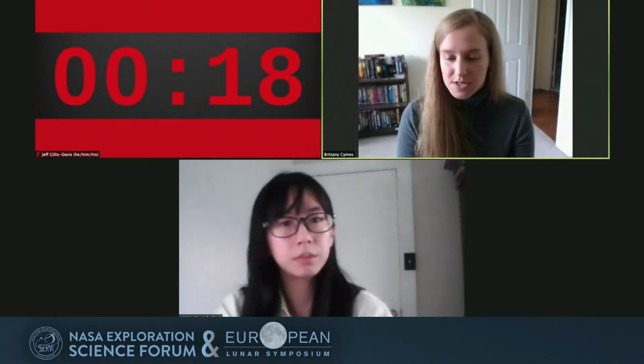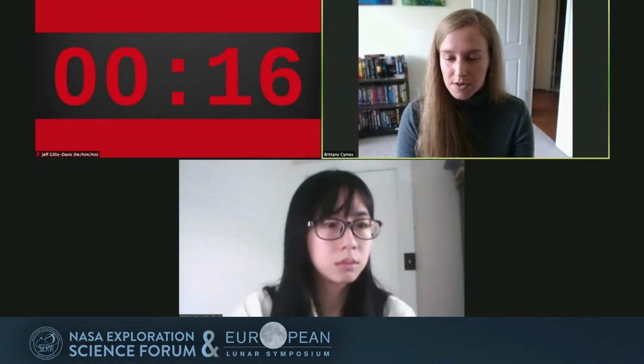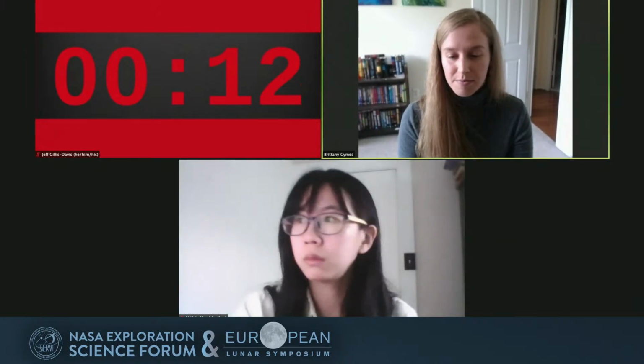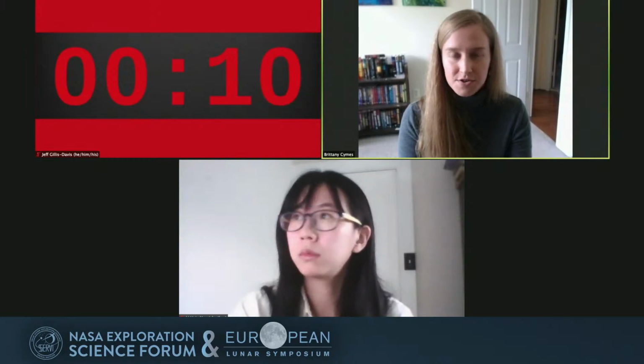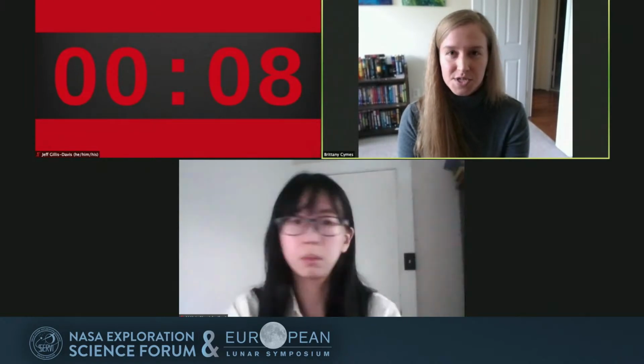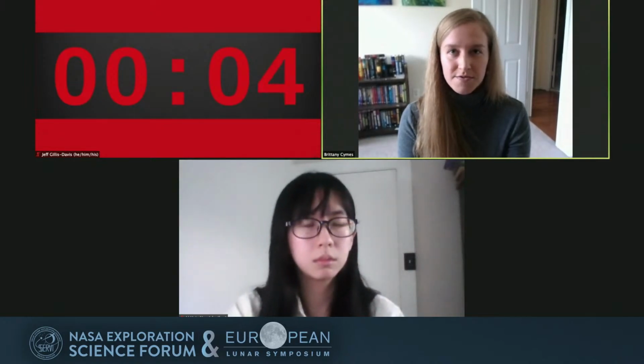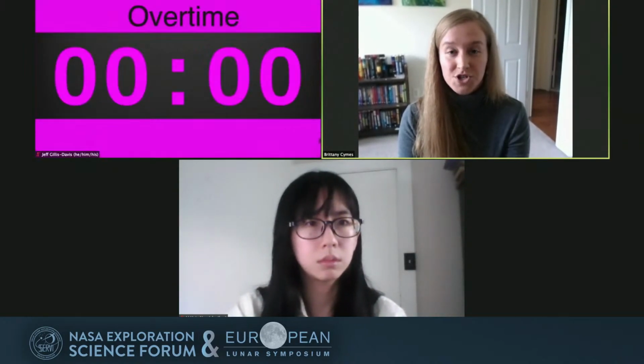Brittany, did you do any particle size measurements to determine if there's any particle size effects? So the particles in the pigeonite lamellae max out at about 10 nanometers, and we do get more fine population distributions in the augite. So they're there, they're very fine and very small. So I think that their formation is simply slowed because of the higher oxidation state in the augite.